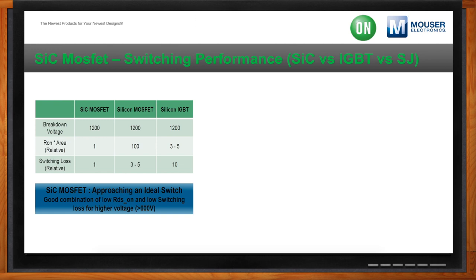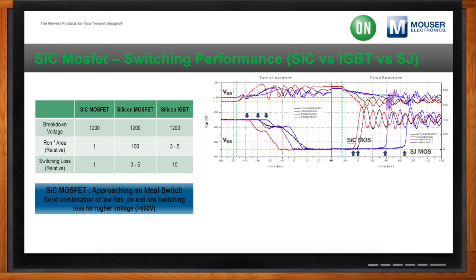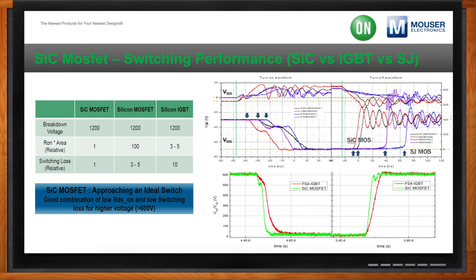So in turn, we can see some waveforms. The waveform on the top compares to our silicon MOSFET, our superjunction. There are some arrows that show the turn on and turn off of the silicon carbide, and you can see that it's much quicker than the superjunction or the silicon MOSFET. On the bottom graph, it shows some switching waveforms compared to IGBTs. You can see that there's no tail current, and you can see the speed and stability of the switching. All that area in between the green and the red is losses in your system. When you're switching this over hundreds and hundreds of hours and you're paying for all this power, you're losing all that power. Right. That's where you really get an advantage in the switching performance of silicon carbide MOSFETs.